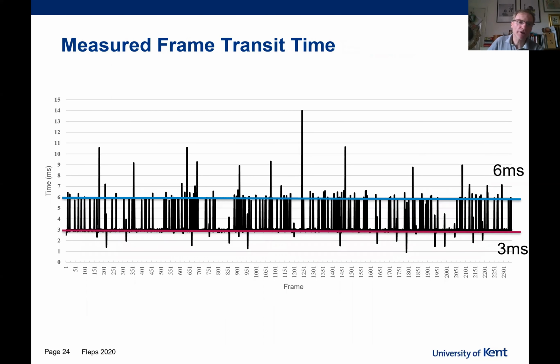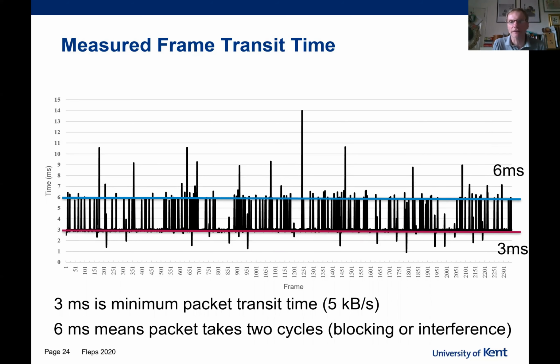Okay, so the measured data packet transit time is shown on this slide. Effectively, the cycle in its usual form should take 3 milliseconds, and we can see that the red baseline establishes most packets do indeed take 3 milliseconds to arrive at the reader. But there's a significant number of packets which are taking 6 milliseconds, or some of them even longer. If we take the 3 milliseconds as the minimum packet transit time, which corresponds to about 5 kilobytes per second, the 6 millisecond packets are essentially taking 2 cycles to arrive.